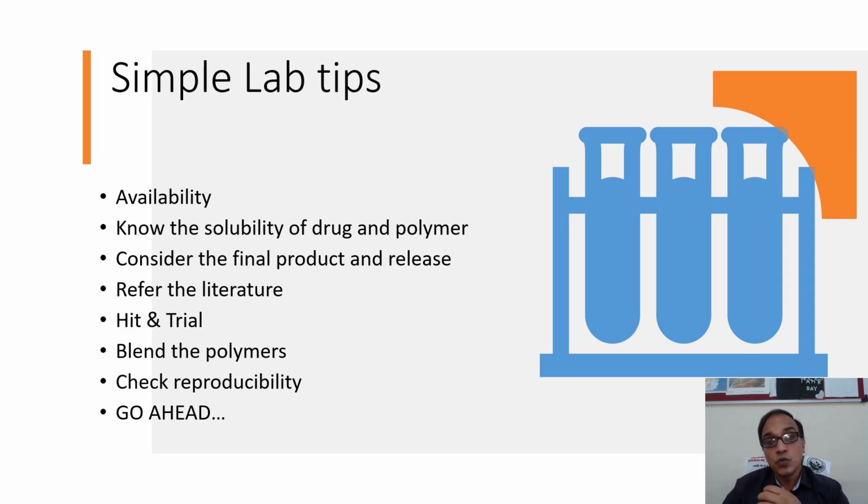What do we have to do now? We will have to make a blend of hydrophilic and lipophilic polymers. Now you take some amount of hydroxyethyl cellulose and some amount of sodium carboxymethyl cellulose, which is a hydrophilic polymer. You take ethyl cellulose, no issue, but you add some sodium CMC, provided it is compatible with the drug. Then make a blend and use it. So what will happen? The controlled release of the drug will be ensured, because ethyl cellulose is ensuring the slow release and sodium CMC is allowing the slow diffusion of the drug across the matrix to the circulation or to the body.